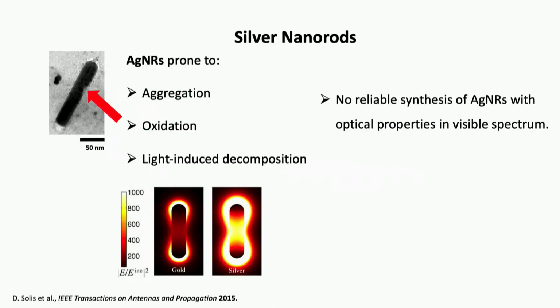The answer to that is relatively simple. Silver nanoparticles themselves are very prone to aggregation, disintegration, and oxidation. You can see here in the TEM image, it looks like someone has taken a big bite out of it. That happens very quickly with silver nanorods. Additionally, there's not really a reliable synthesis of low aspect ratio silver nanorods with tunable optical properties in the visible spectrum.